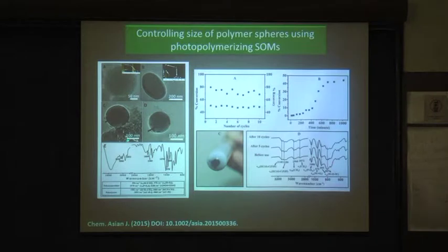And finally, we see this oxometalate ripping off the surface. This is the hydrophilic part, and this is the central hydrophobic polymer core. And finally, we have this polystyrene coming up. This is the transition state, or the intermediate state we could see. And you see all the bands that are present of polystyrene as well as the oxometalate. And what we see at the end is the macroscopic phase separation. This is the blue one, the reduced oxometalate that comes off from the dispersion, and you have the polystyrene. And you see here also the kinetics is sigmoidal.